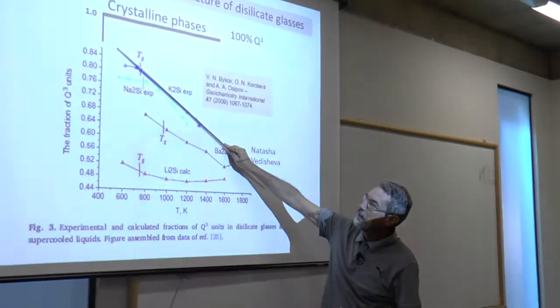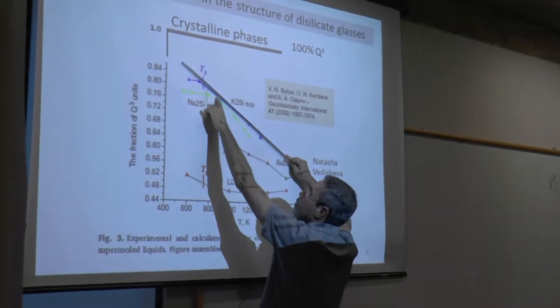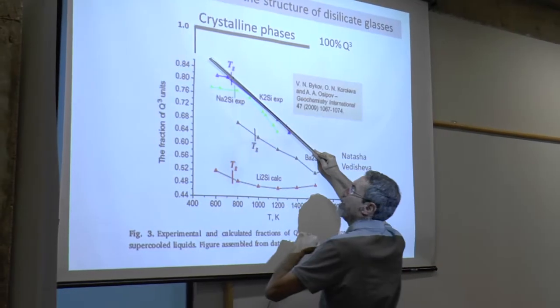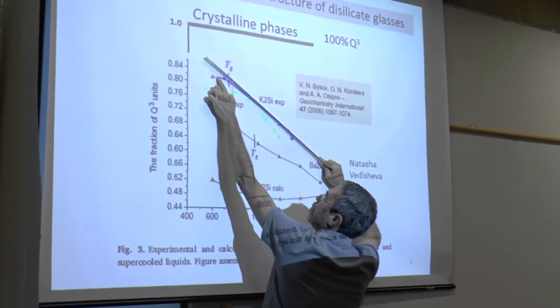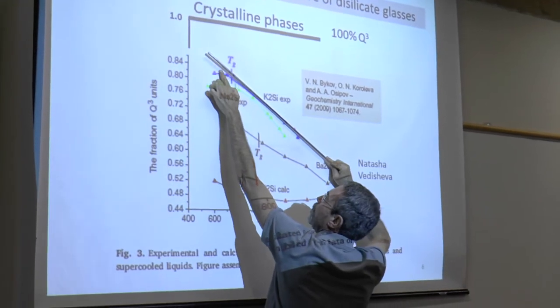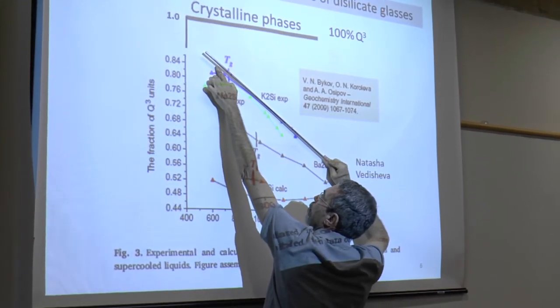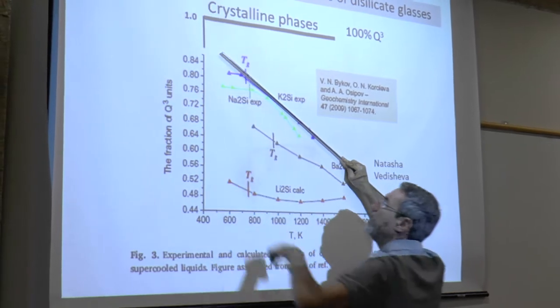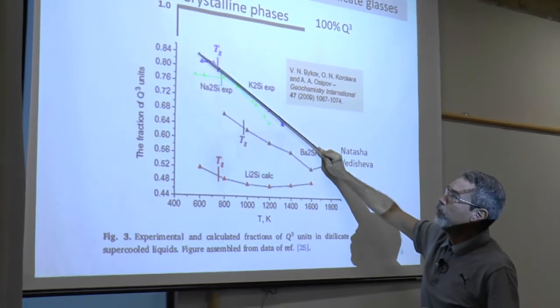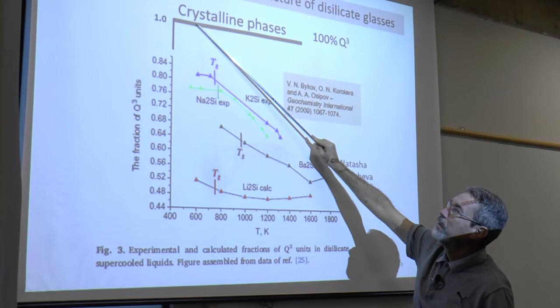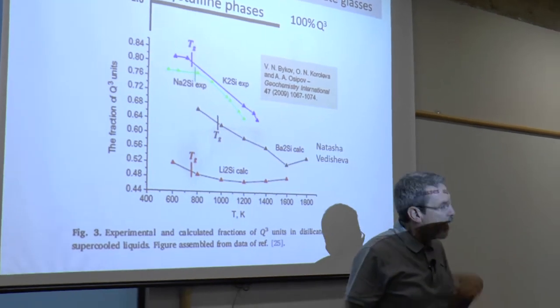These glasses here are relaxing. All glasses are relaxing towards the supercooled liquid. This will be the supercooled liquid extension. So the relaxation process would be moving from here to here. But it doesn't stop here. It continues to go towards the crystalline phase, if we wait long enough.